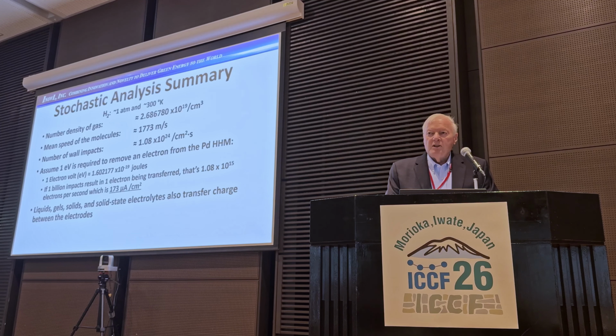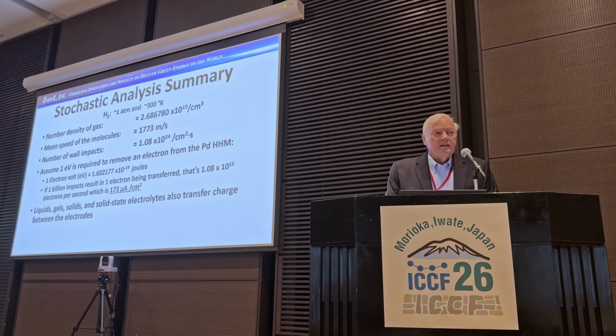And if it takes 1 billion impacts to knock off one electron, that will produce about 173 microamps per square centimeter. Now, recall the slide that I showed where we were producing about 700 microamps. That was for about a 4 square centimeter surface area. So this is amazingly close. And all we have to do, if we say it was really 0.68 electron volts, then that increases the number, and that's a number that's been reported by John Paul and others, and we've measured that too. So we believe that this analysis tends to confirm the contact electrification.